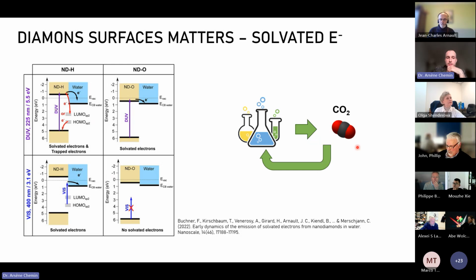One very nice paper that showed that is the paper from Büchner et al. from 2022, where they looked at the emission of solvated electrons from nanodiamonds. And they were able to show that solvated electrons were produced from the photoexcitation of H-terminated nanodiamond, but not really, at least not in the visible range, by the photoexcitation of oxygen-terminated nanodiamond. And the way they explained that at that time was the existence of some surface states of the sp2 carbon that enable the visible excitation of solvated electrons from the hydrogen nanodiamond.